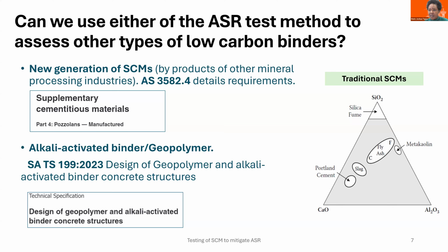Now, alkali-activated binder geopolymers, I think, are a more controversial topic because SCMs are known to mitigate alkali silica reaction, but alkali is known to aggravate ASR. So basically, you would almost expect that one would offset the effect of the other. But again, we've had a good move in this space. So there's SA TS 199, recently published, with the design of geopolymer and alkali-activated binder concrete structures.